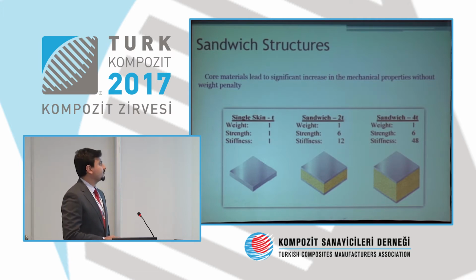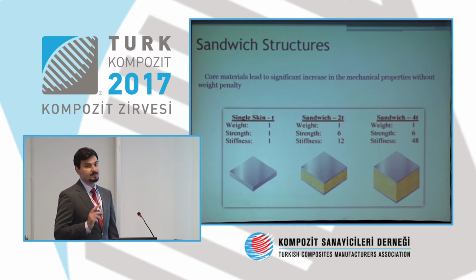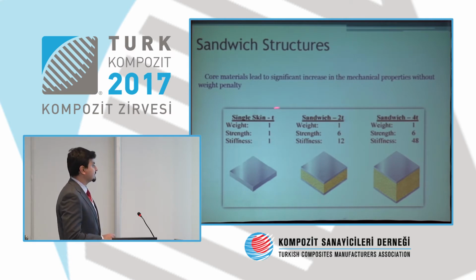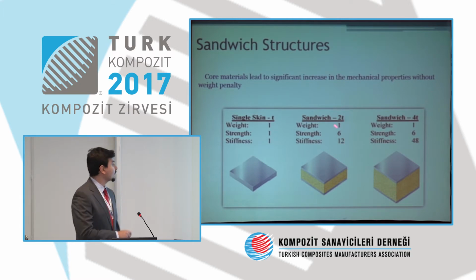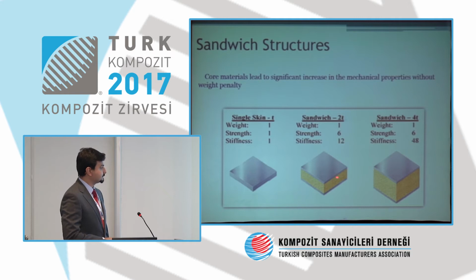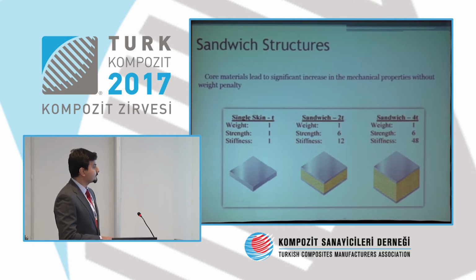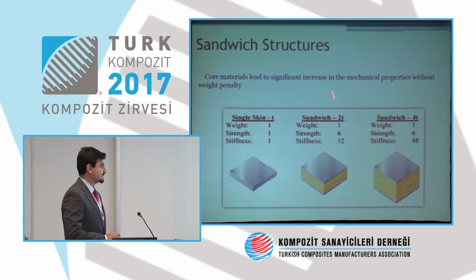Here is the effect of core material. Core materials lead to a significant increase in the mechanical properties without weight penalty. Here is the single skin. The thickness T and weight is 1 unit, strength is 1 unit, and stiffness is 1 unit. If we increase this core thickness to 2T, the weight is the same, but strength increases to 6 times and the stiffness increases to 12